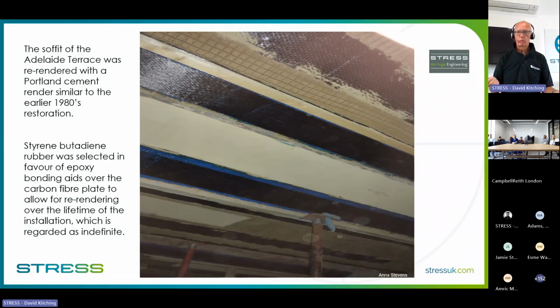Now, we talked about the render falling off, and at some point in time, 30 or 40 years ago, it had been repaired or replaced. They hadn't done it with lime mortar. They'd actually done it with a sand and cement render, which we were really surprised about. And because it's a heritage building, you actually have to match what's there at the time. So in fact, we ended up putting back a sand and cement render. We were allowed to add some SBR, which gave it, it handles better and it's stickier and it will bond better.